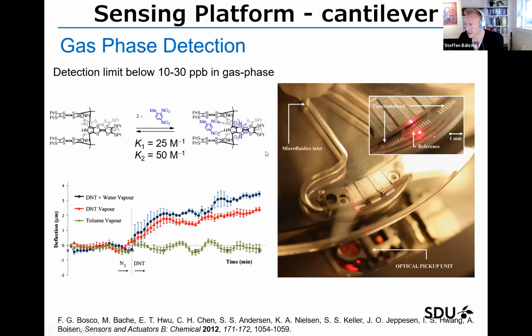And at the same time, my former supervisor, Jan Jeppesen, also reported that this dipropyl TTF calix[4]pyrrole could function as a sensor for gas phase detection. And this was a similar method, but they used optics instead of electrical resistance. So this is a modified CD-ROM where they adsorb the calix[4]pyrrole, and then they could expose it to dinitrotoluene vapors, and you can also see that there's a positive response. So these are two examples where they actually made it as a sensor. But my goal is to explore the spectroscopic methods.